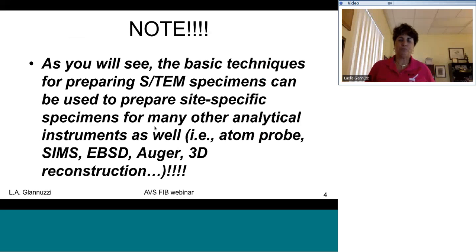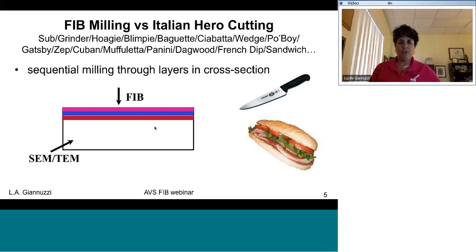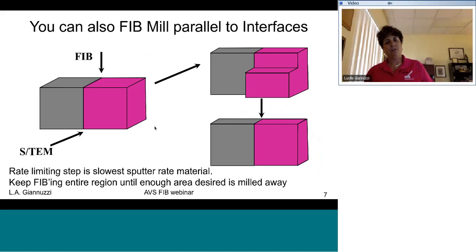All right. The type of sample prep that we're going to be talking about is also perfectly applicable for atom probe, SIMS, EBSD, Auger, 3D reconstruction, etc. Getting back to this slide, it's basically the same type of thing. We're going to be sequentially milling through our different layers. We can also make plan view samples, which I'll talk about a little bit later. So remember, we can make our samples of just the tomatoes in our Italian hero if we want to. Note also you can mill parallel to interfaces as well. Remember that the rate-limiting step is the slowest sputter rate material.